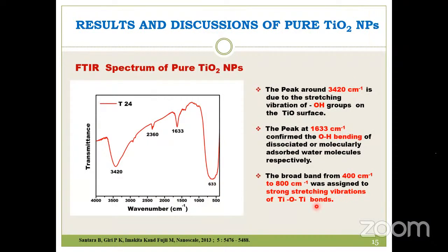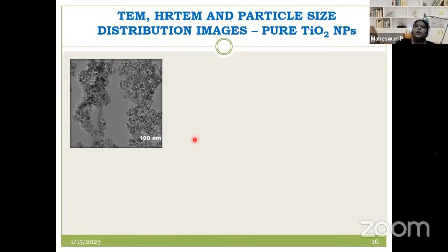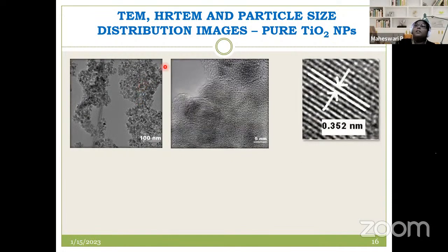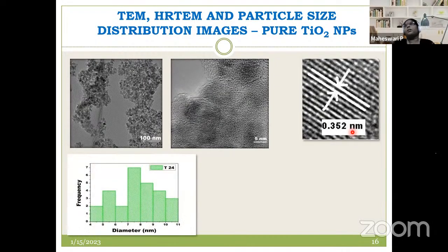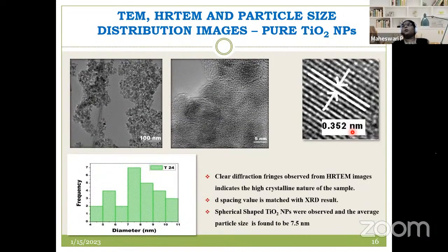Apart from this, there is TEM and HR-TEM analysis. This is highly preferable and a strong confirmation. In the case of TEM analysis, you can see at 100 nanometer resolution what is pictured here. HR means high resolution, where you can even go down to 5 nanometers. Under that, you can see there are patterns. These are the diffraction fringes, what we call the lattice spacing. When we measured this, we found the spacing to be around 0.352 nanometer, which clearly matches the XRD. From that, the particle size was estimated to be 7.5 nanometers. So this covers our synthesis of TiO2 nanoparticles.